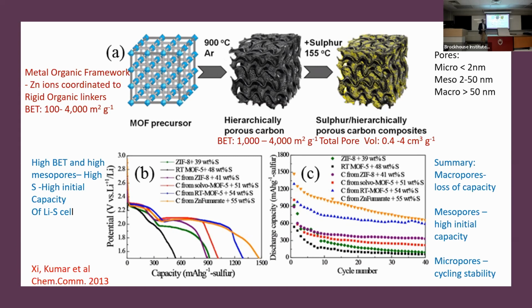I have not quantified it here, but we've been able to quantify what might be the right optimization between these three pores, so that you get not only as high a capacity as possible, but also keep it stable. It's no good having a very high initial capacity if after a few cycles the capacity has gone down. So it's very critical to keep it stable, even if the initial capacity is lower. That's more important, because there is a requirement of a minimum capacity and a large cycle stability. If this was going into electric vehicles, drones or aerospace applications, you can imagine the cycle life is so important. It must at least be comparable to lithium-ion batteries, which is about 1,000 to 2,000 cycles.